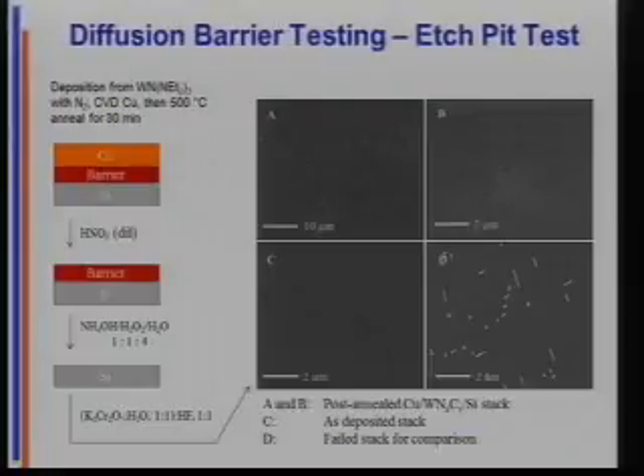And so if your barrier fails, you get something that looks like this, where these little white lines are what are called etch pits from etching out copper silicide. But that's not our barrier. That's one that didn't work, okay? So C is what happens as deposited with no annealing. This is our barrier. And A and B are our barriers tested under these conditions. No etch pits, even at high magnification. So these barriers actually do pass the diffusion barrier test.